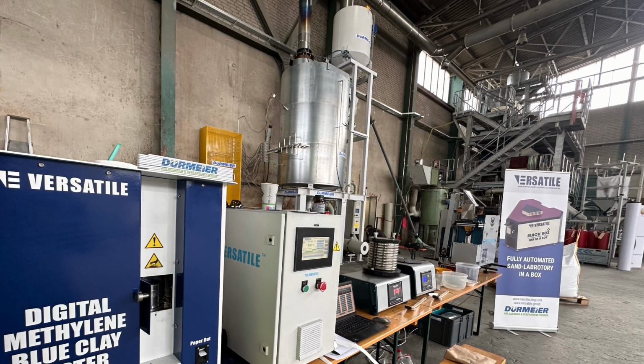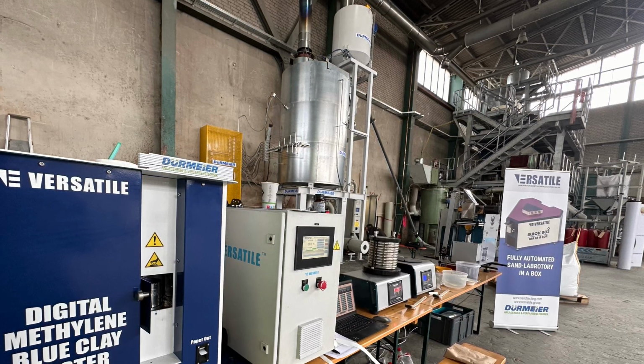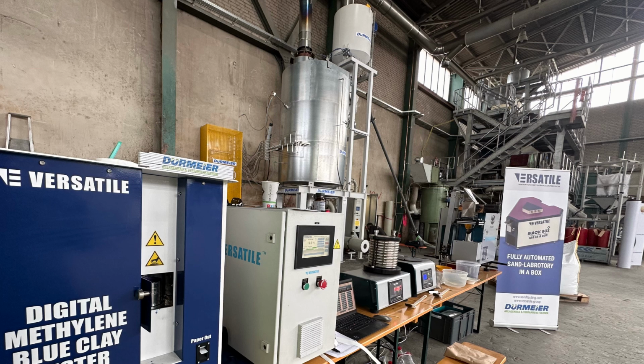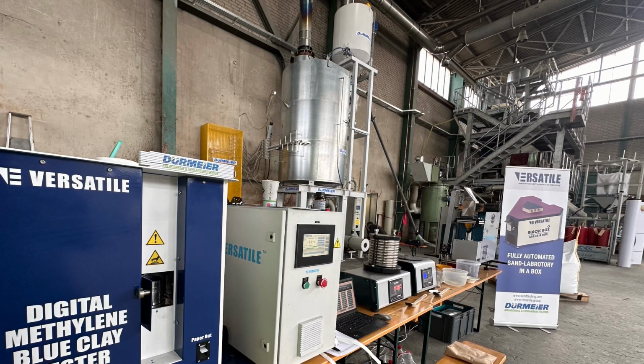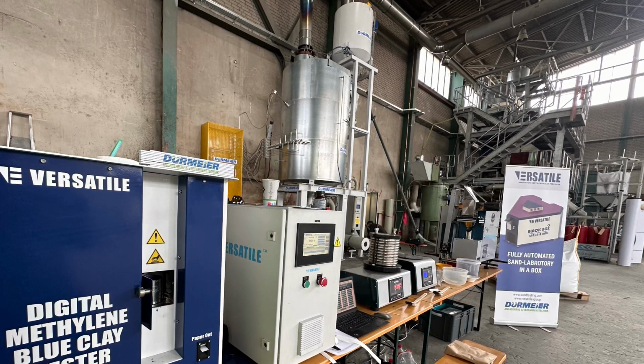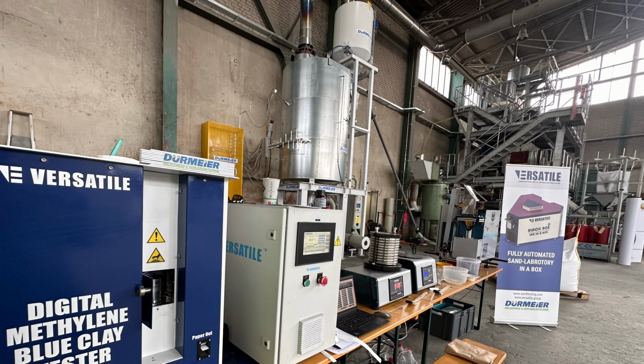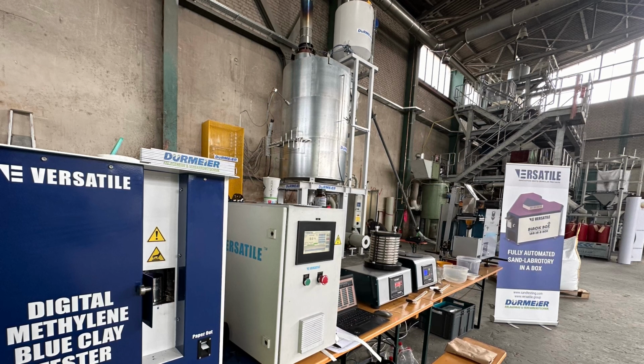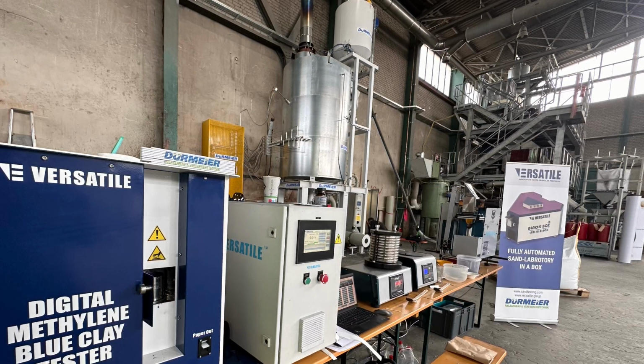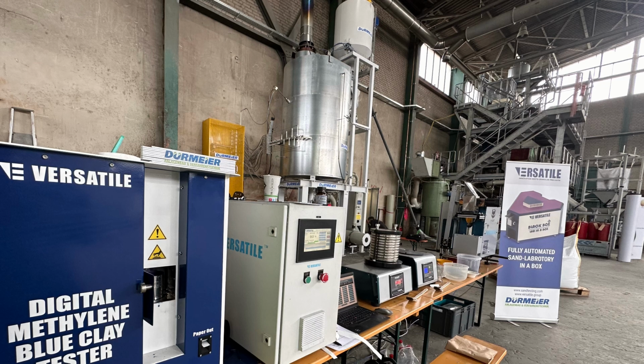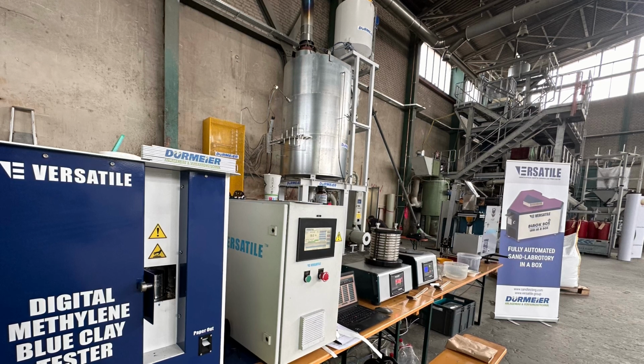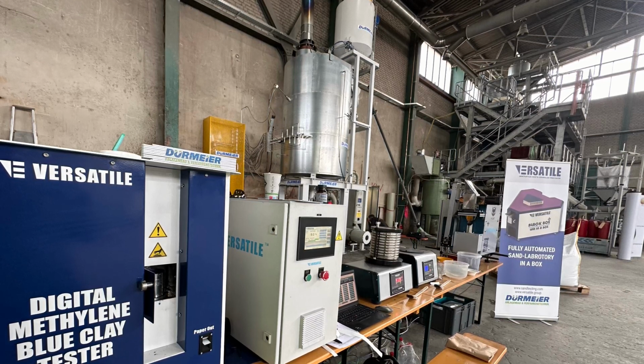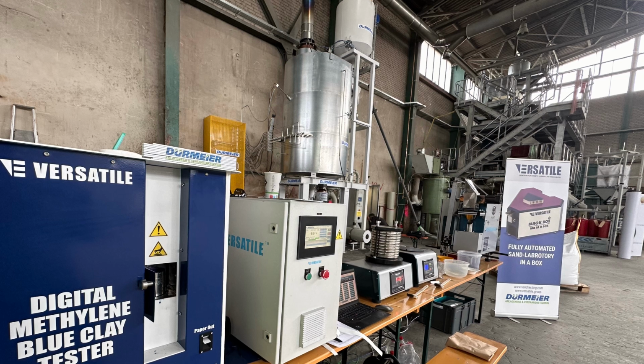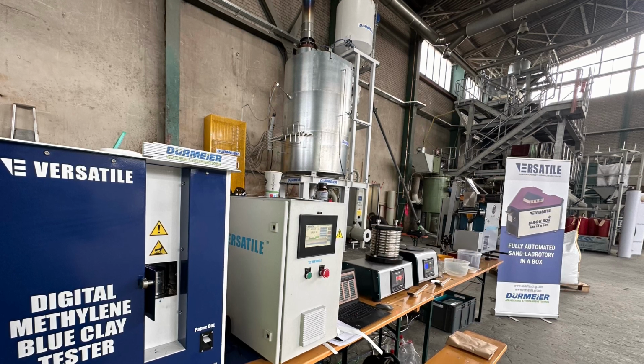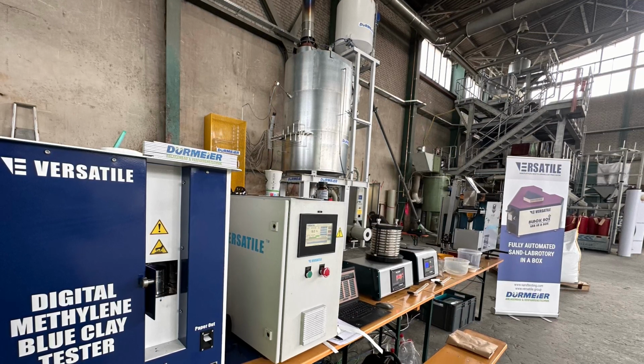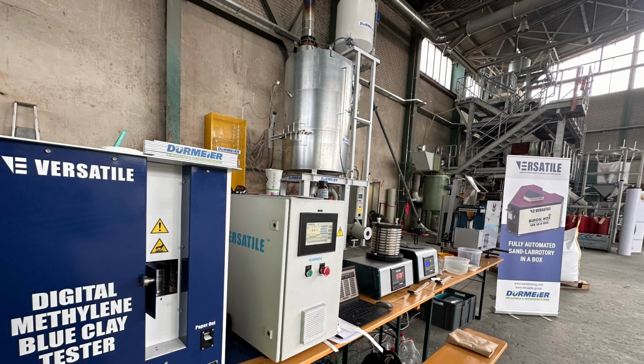Okay. We also hear about the AFS grain fineness number. Is that a test? It's not really a test procedure itself, more like a calculated result. It comes from doing a sieve analysis, shaking the sand through a stack of screens with different mesh sizes, to see how fine or coarse the sand grains are. Precisely. The GFN gives you a single number that summarizes the overall particle size distribution. It affects the final surface finish of the casting and also influences that permeability we just talked about.